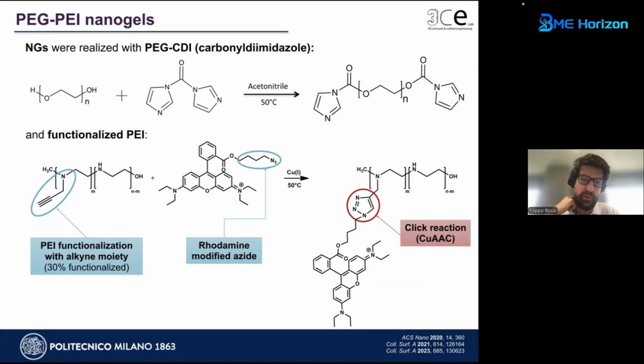And the other polymer we obtained is polyethylenimine, widely used in gene delivery, that in this neat form is toxic, while cross-linked not. So we introduce a post-polymer functionalization, we said before, in this case for the tracking, but it also, spoiler, we will see that the chromophore is important. So we click them with a propargyl group in the polyethylenimine and an azide group in rhodamine. We obtain the polyethylenimine clicked with rhodamine.